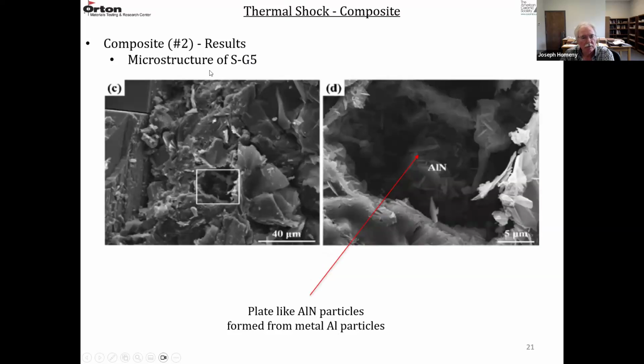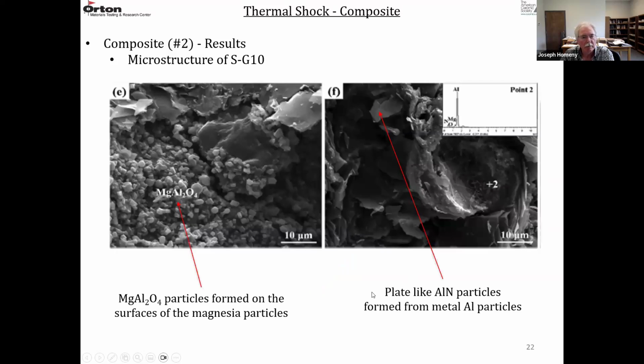And basically, they're showing the same thing in SG5. So this area here, you see to the right. And again, you see these plate-like structures. So that's the aluminum nitride again, that's formed from the aluminum metal that's present. This is an SG10.